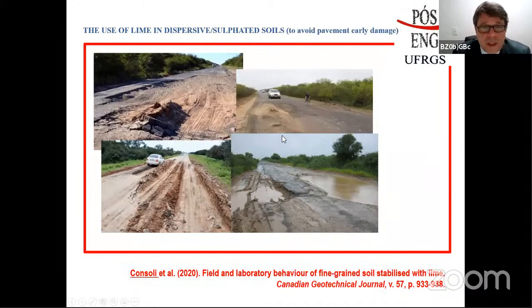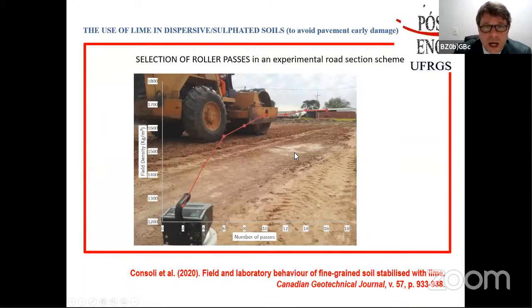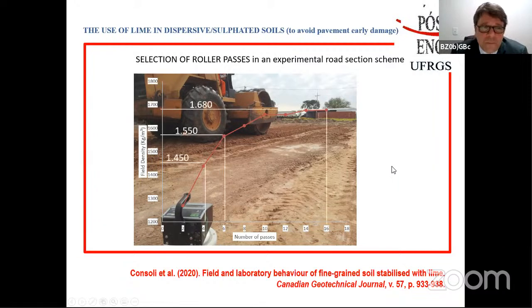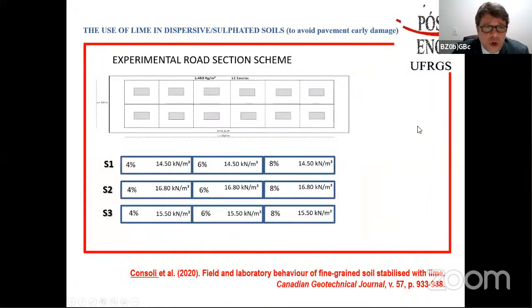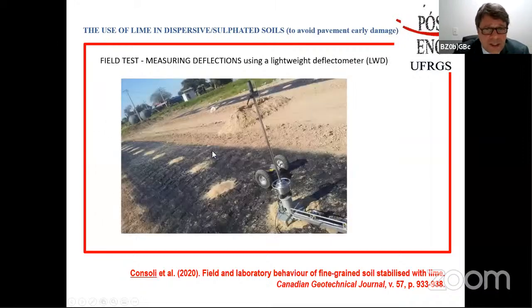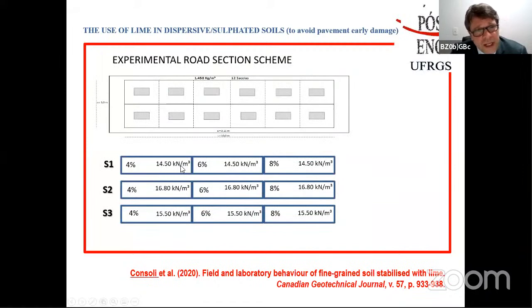And we can see here the region before, what happened without any kind of improvement. And then we published in the Canadian Geotechnical Journal a test trial that we carried out in a road section at the place where we have this soil, with the compaction and the number of passes that we had. And then we chose 3 different densities in the field with different amounts of lime also. And we built different sections with different dry unit weights and different amounts of lime. So as I said, it was published last year in the Canadian Geotechnical Journal.